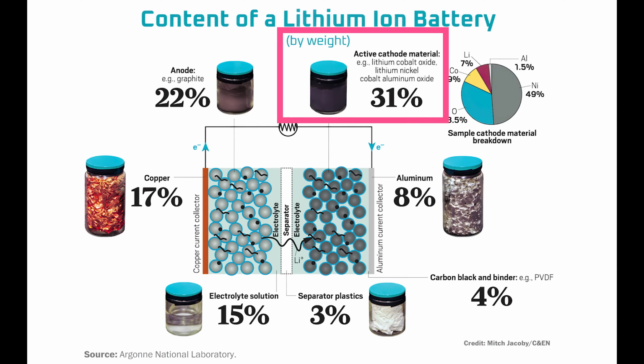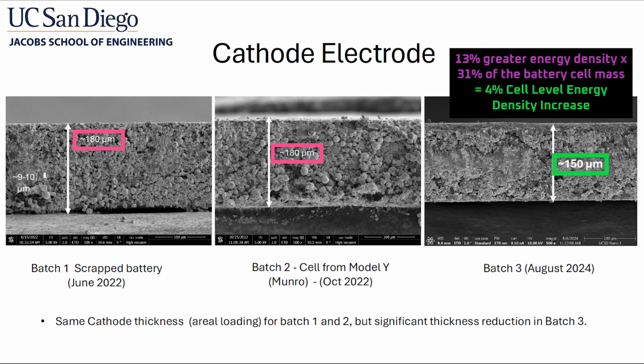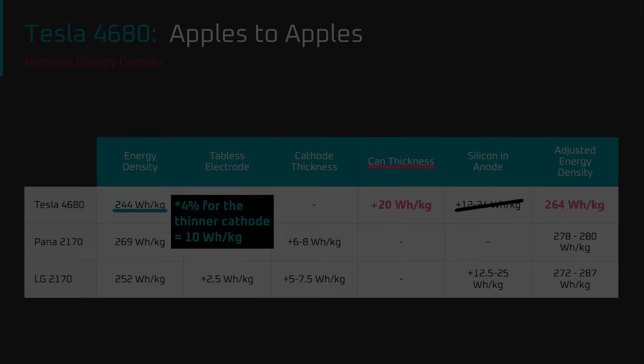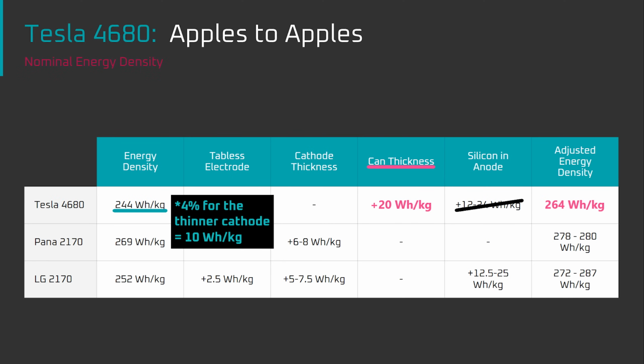No, because the cathode of a lithium-ion battery cell is about 31% of the total weight of the battery cell. So if we multiply 13% by 31%, that's roughly a 4% energy density increase. 4% times the 244 watt-hour per kilogram baseline of the generation 1 4680 is 10 watt-hours per kilogram.